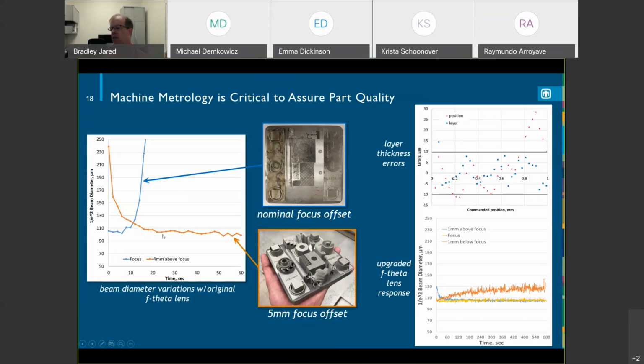And we figured some of this stuff out, applied some offsets, and actually this is essentially the same build. And this is without an offset change. This is with, and you can see the dramatic difference in the process itself. And so the key here is that a lot of people in the additive space buy equipment and kind of plug it in and don't really understand their material, don't really understand their machine system. And these are all things that you have to characterize. These are not necessarily difficult things to do for the most part, but these are critical to getting a process that's going to be in control and within specification.